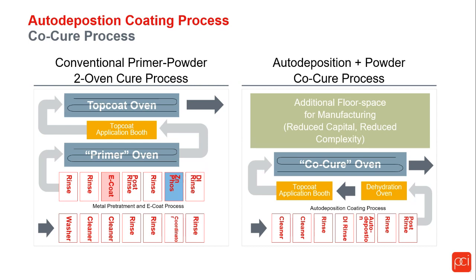This is a representation of a comparison of the auto-deposition system versus a traditional conversion coating, primer, and top coat system. The one on the left, as you see the parts enter here, would go through the standard conversion coating process, move up, conversion coat, and this is an E-coat application, primer layer, and then to a full oven to cure the primer, to top coat, which would be powder coat, and then to another cure oven.